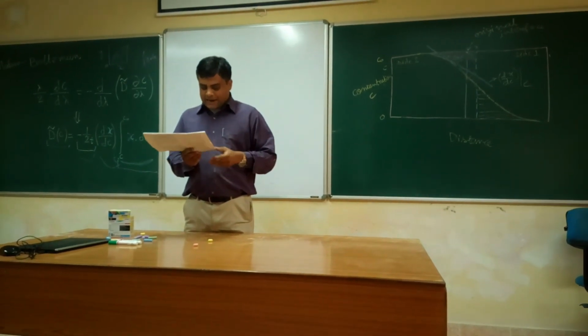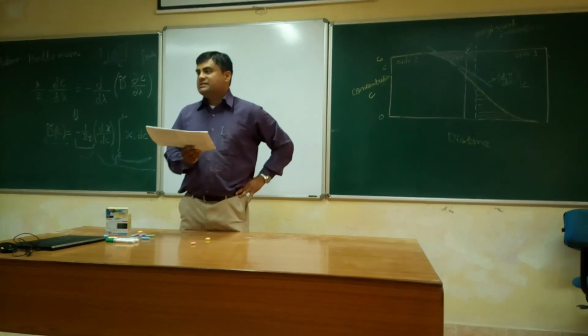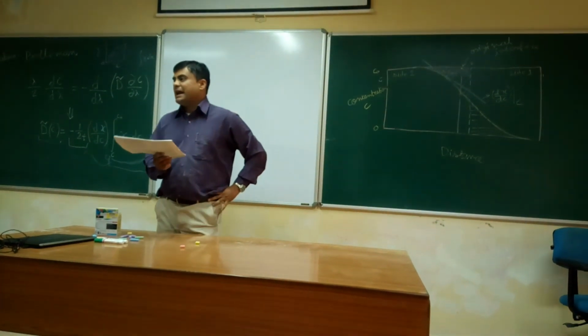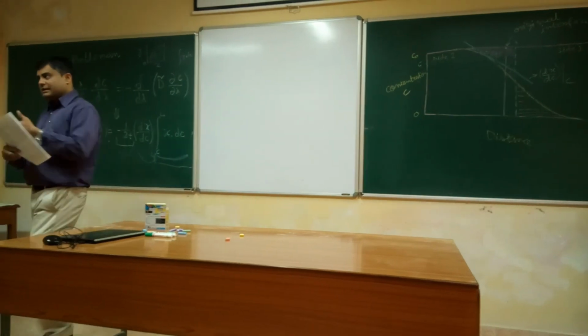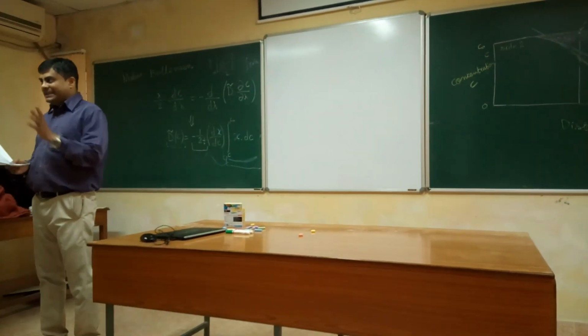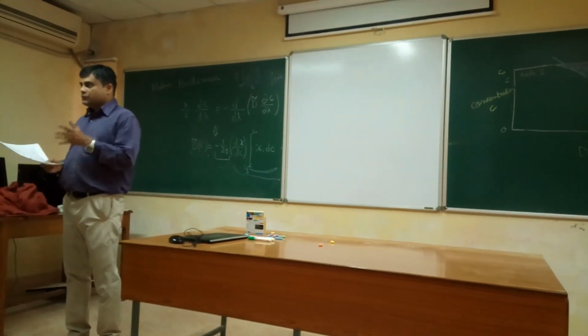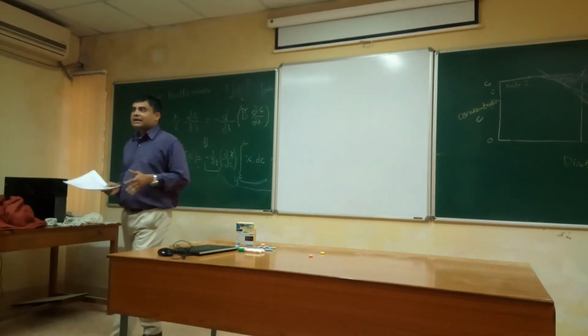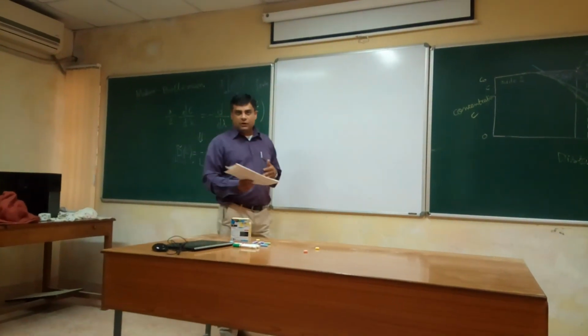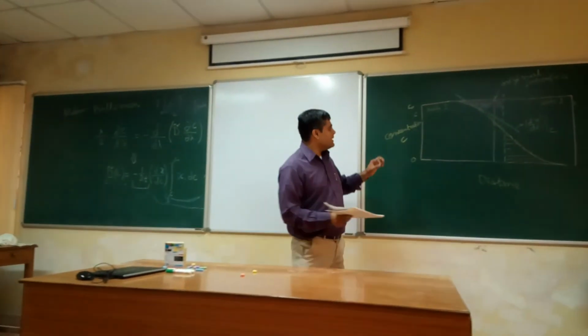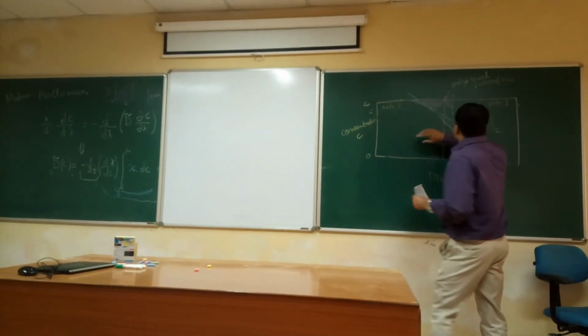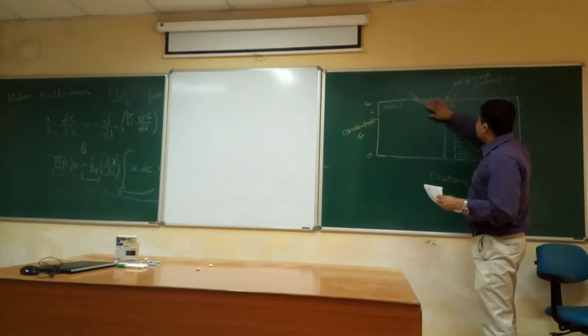Origin is that plane across which the net flow is 0. The net atomic flow, because two atoms are moving at different rates on both sides, is 0.